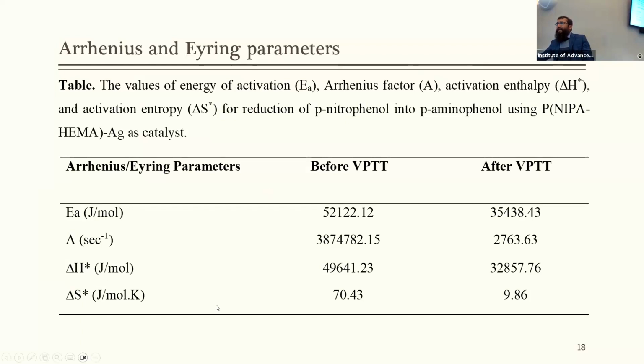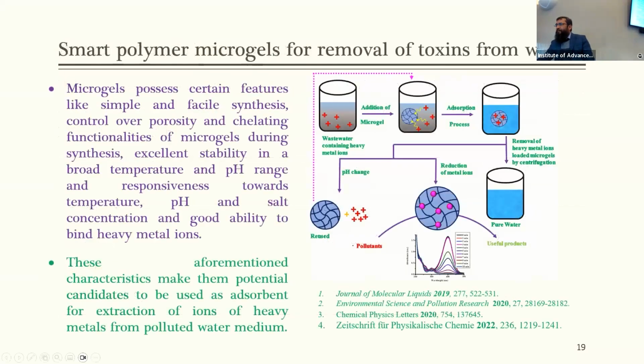The Arrhenius and Eyring parameters were evaluated before and after the volume phase transition temperature. The positive value of entropy of activation indicates that the process of activation is endothermic and entropy driven. We have used the hybrid microgel system as a catalyst to degrade toxic chemicals into useful chemicals. For example, we were able to reduce 4-nitrophenol into 4-aminophenol, which is a green useful product.